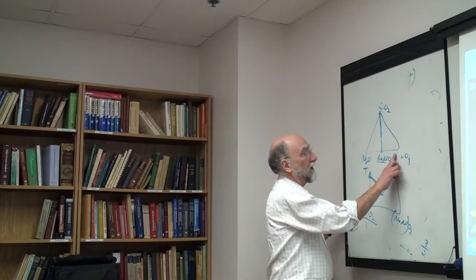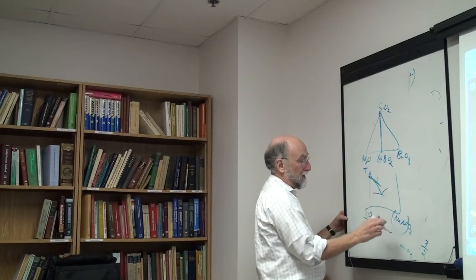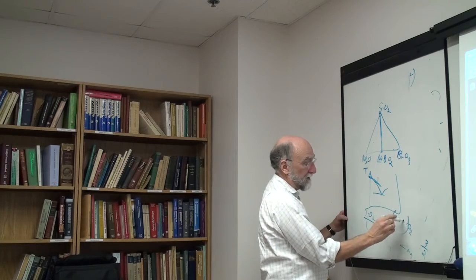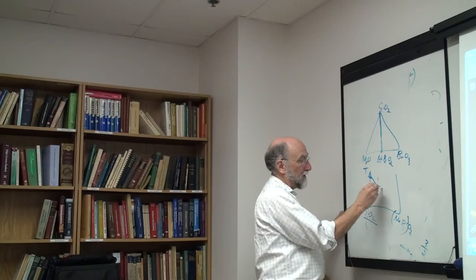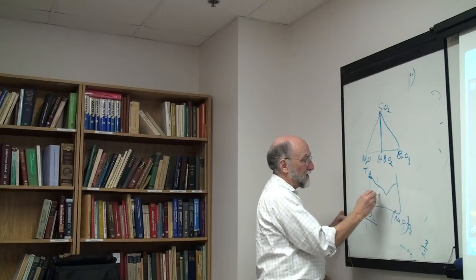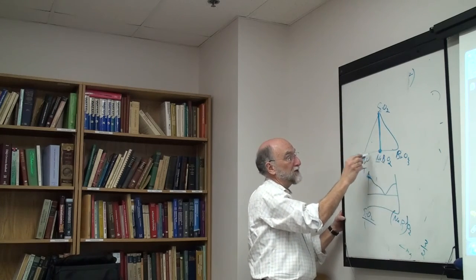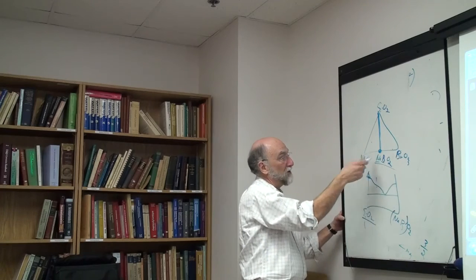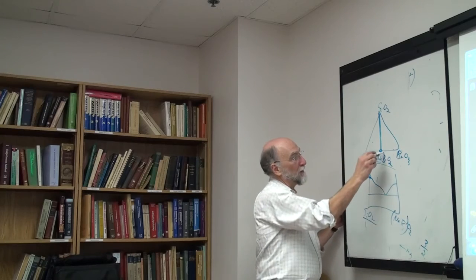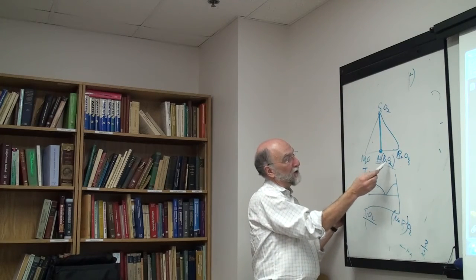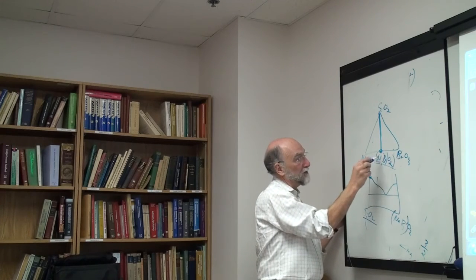And when we did it with boron, I showed you the other day, this was boron, so you go to NaBO2, and here you can go all the way across. And here now there's a little bit of deviation from ideality in the whole system, but this is going right across here from SiO2 to NaBO2. Remember I said in the sodium borate system you got all these complicated borates and tetraborates and 3 and 4 coordination, but one might imagine that NaBO2 could have the silica structure.